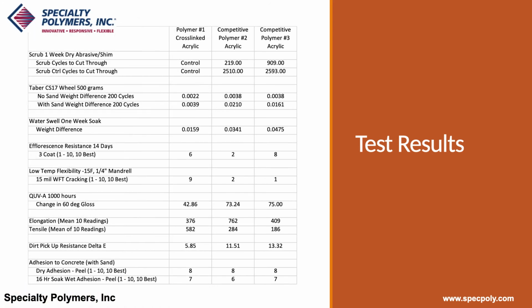These are the results of the testing of the competitive polymers. You can see that polymer number 1 with the crosslinking was much better for abrasive scrub resistance, for low temperature flexibility, for tensile strength, and for dirt pickup resistance. This may indicate a better balance of abrasion resistance and hardness than the competitive polymers.